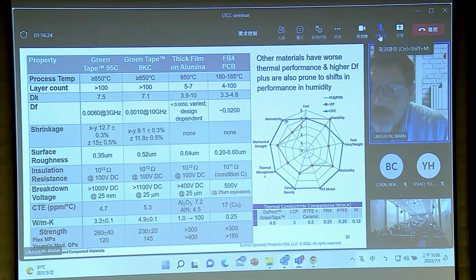But a lot of the other things, LTCC is hermetic, it's stronger, has much easier thermal management design. Because of the higher dielectric constant, you might be able to get higher circuit densities without having a thermal problem. We have a really good thermal expansion coefficient match to the semiconductor devices that are powering the circuits. LTCC is well known for being a very high reliability material because of all the other properties we talked about before. Dielectric constant can make something smaller, so the footprint can be smaller and the weight can be smaller. And so it looks really good. LTCC looks very attractive from a radar plot perspective.